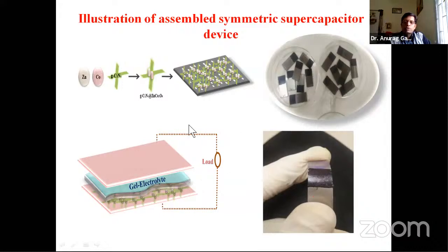And then, to make the full cell, firstly, on the bottom, it is a nickel foil. Over that, this composite material is coated. After that, there is a gel electrolyte, a combination of PVA plus KOH. This gel electrolyte is formed separately, and then we coat it over one electrode. Then we put a second electrode on top of this, so that we can have contact on both sides. Then this final assembly can be prepared. That's how you can prepare the full cell.